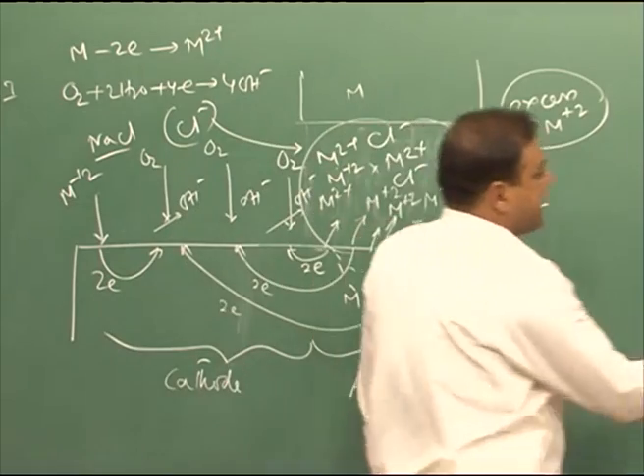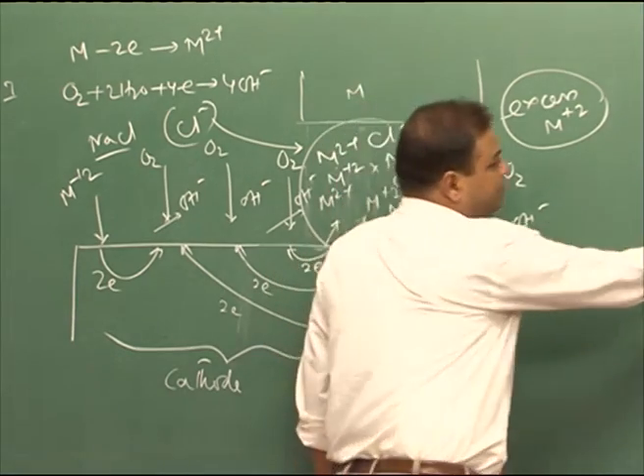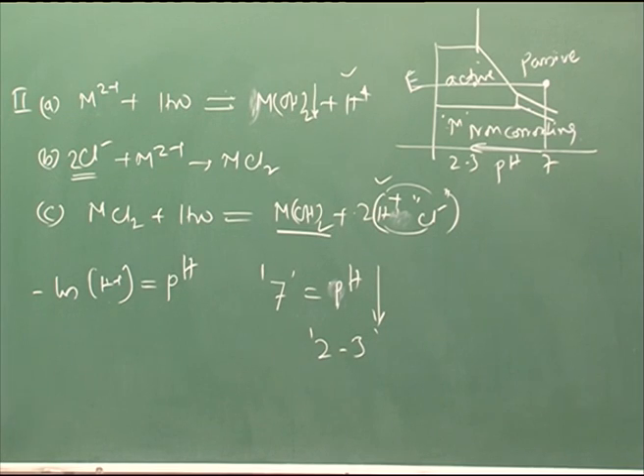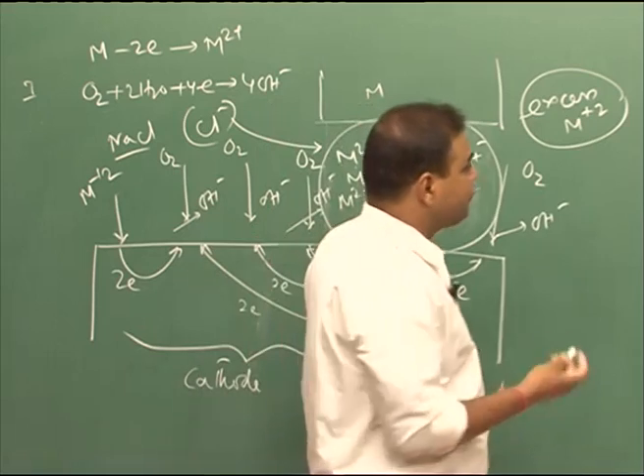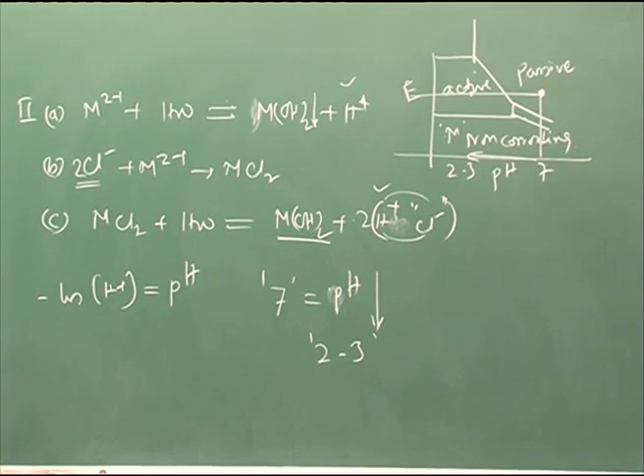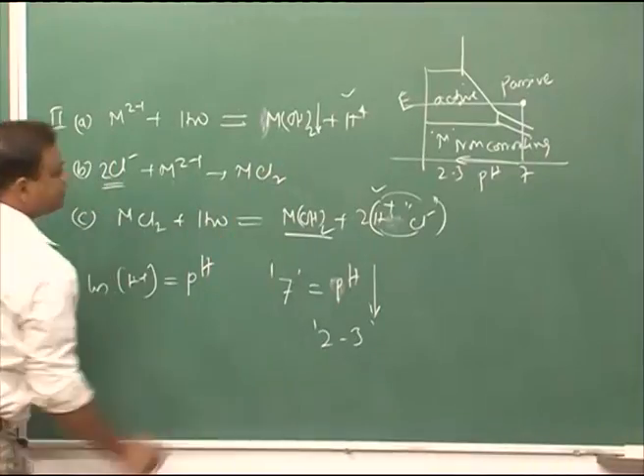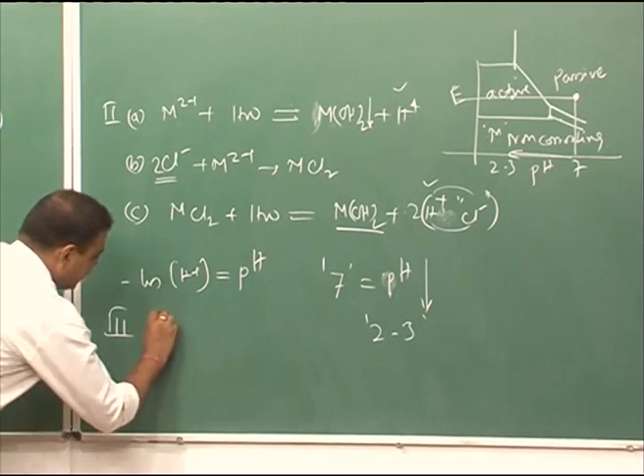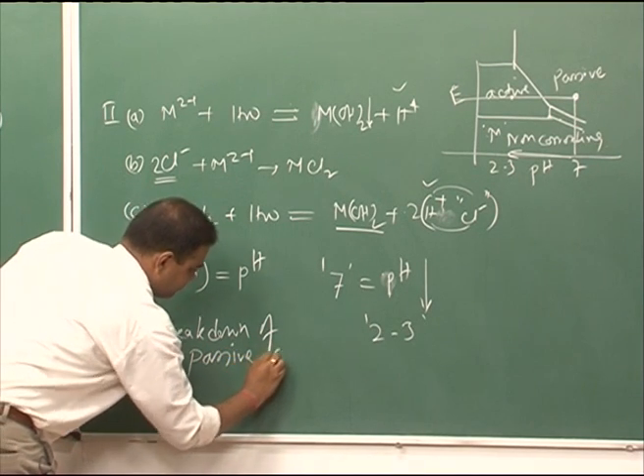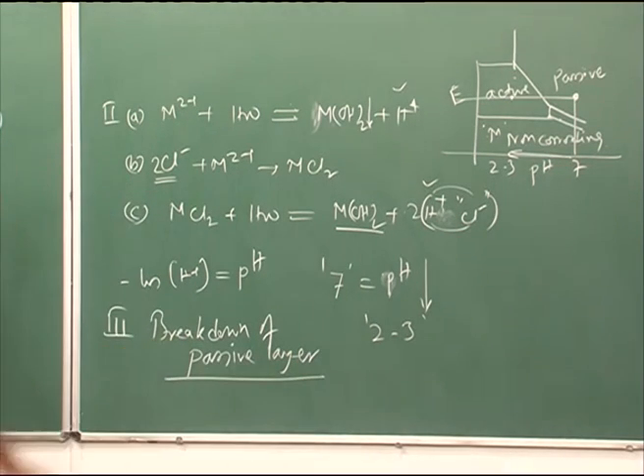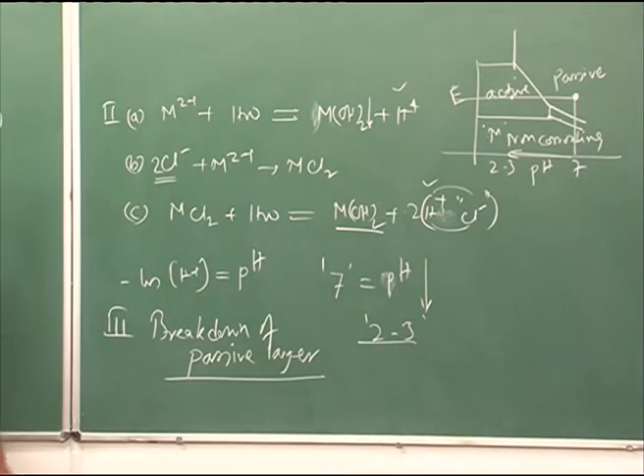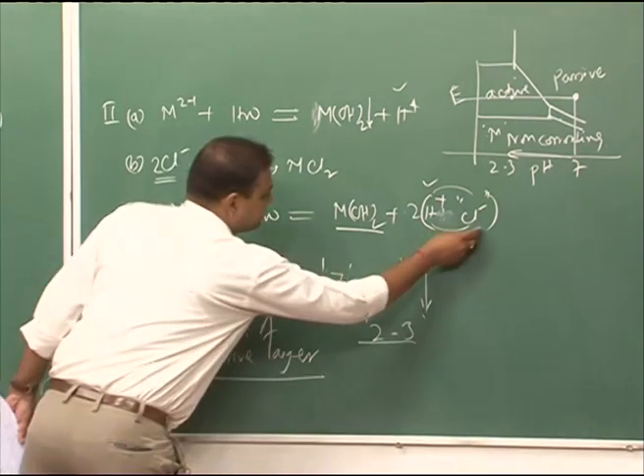If it is a passivating metal with high chloride ion concentration in this zone, the chloride ions try to break down the passive layer. So two phenomena occur: in the third stage, acidity increases (pH drops to 2–3) and chloride ion concentration increases. In stage three, we have breakdown of the passive layer, enhanced by the low pH of 2 to 3 (highly acidic condition) as well as the presence of chlorine.